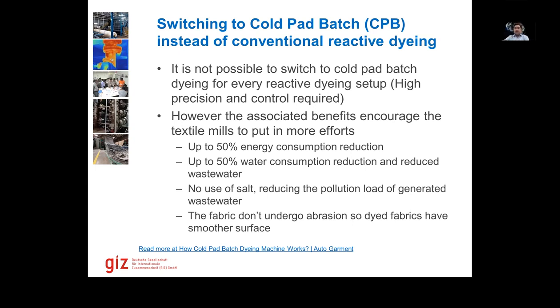As you also saw, high precision and control is required, and the process is slower. So I do not recommend that factories totally shift to cold pad batch dyeing. This can only be done on batch dyeing, as you can see from the name. The continuous dyeing machines cannot be shifted, so only the batch dyeing machines can be shifted. The best way is to go for a newer machine that allows using cold pad batch, rather than converting older technology machines. But never just recommend factories to shift to cold pad batch dyeing. Cold pad batch dyeing here is only shared as information that this is one of the processes.